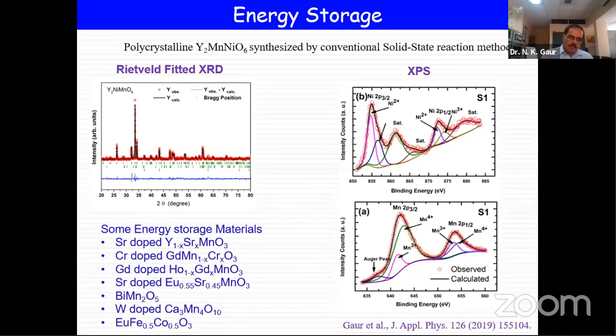So we have also fabricated a few materials, this SrMnO3, some oxide materials. This is GdMn1-xCrxO3, HoGdMnO3, europium strontium manganese oxide, BiMn2O5, W-doped Ca3Mn4O10, and EuFe0.5Co0.5O3. These compounds are also used for energy storage, and work is going on. And these are the materials which we have fabricated in our lab. And the Rietveld fitted XRD for Bi2Mn4O10 we synthesized in our lab. We have shown some of the results.